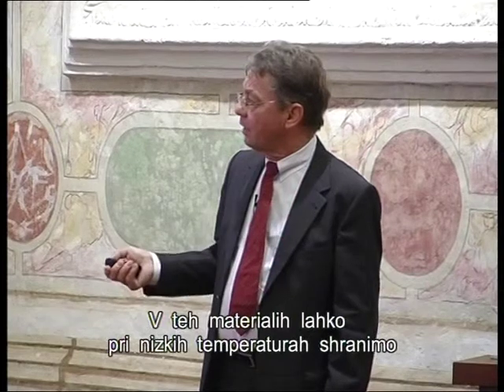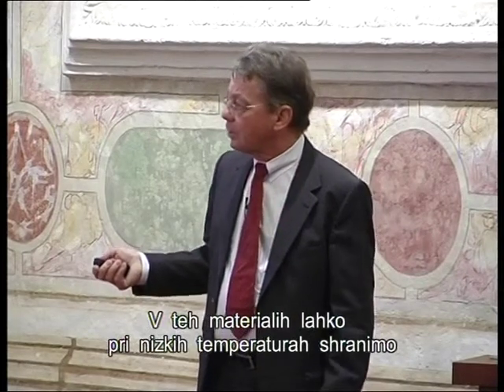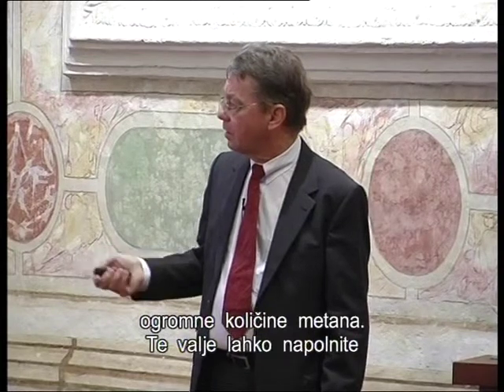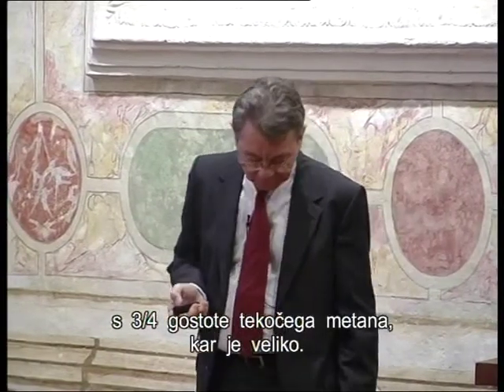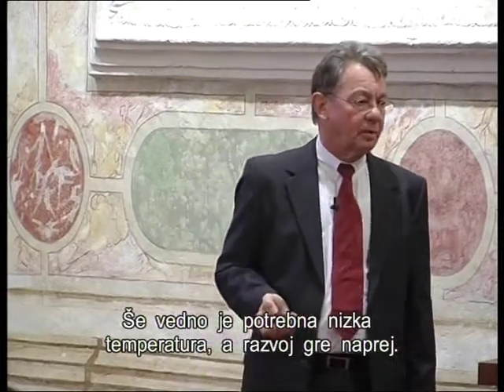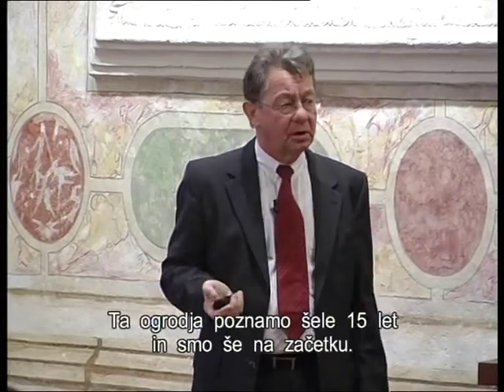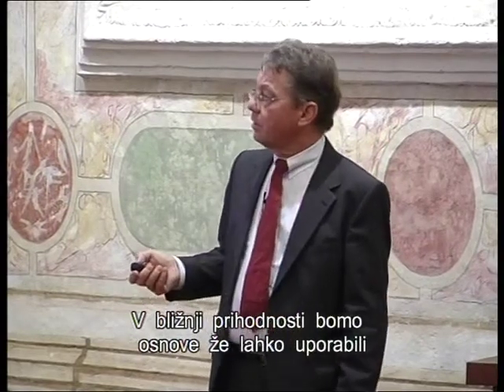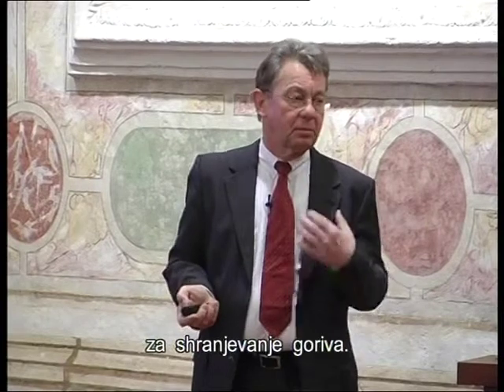And as you see here from the figures I've shown, huge volumes of methane in this case can be stored in this material. So if you fill these holes up with methane, you reach three quarters of the density of liquid methane, which is a lot. It's still at low temperatures, but these are developments which are in progress. These metal organic frameworks are only around for something like 15 years, so we are at the beginning of some development, but I'm pretty sure that in the not too distant future, these materials will be used mainly for that purpose, in my opinion.